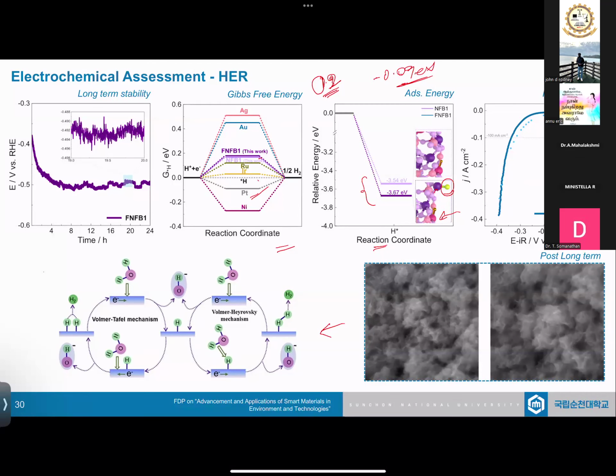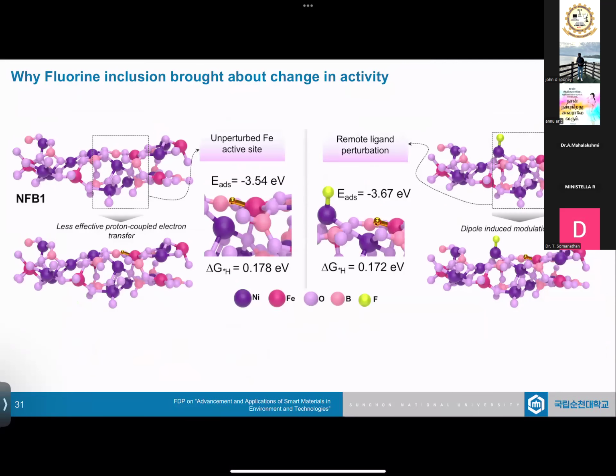Everybody knows the Volmer-Heyrovsky. We did all the required studies. All the radicals were tested, and only the hydrogen is reported over here. But we evaluated every single step, and it's been reported. And we have extensively discussed how the atom is making this happen. So as I said, the adsorption energy is changed, the Gibbs free energy is changed. I'm sorry, 0.17, 0.172. So this is what we got.